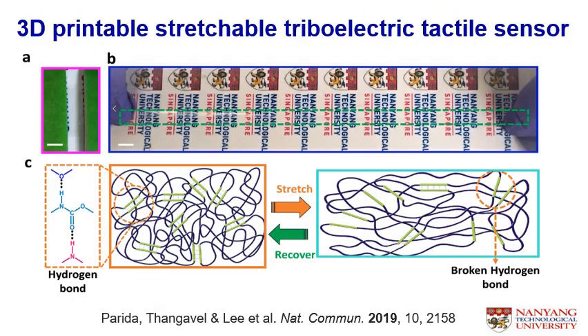Next, we move into triboelectric tactile sensing using a highly stretchable polymer that can be 3D printable. This synthesized polymer has abundant dynamic hydrogen bond that allows dissipation of bond energy during stretching, and dynamic bond breaking and association during the dynamic stretching and relaxing, which allows unfolding of the long polymer chain.